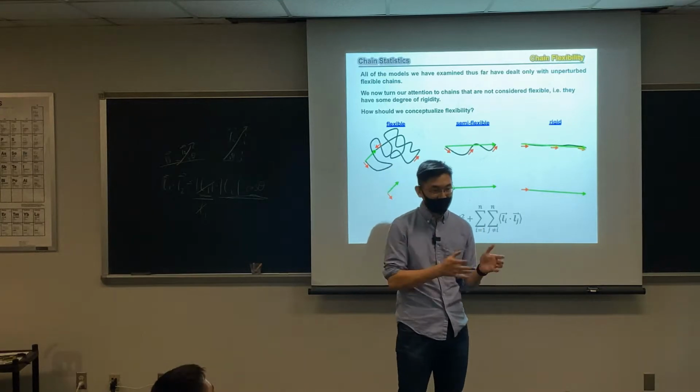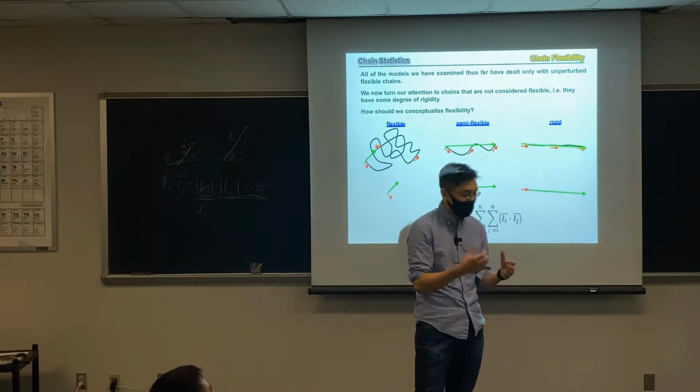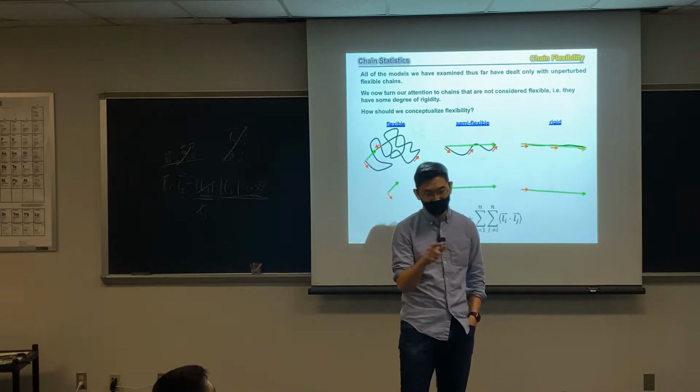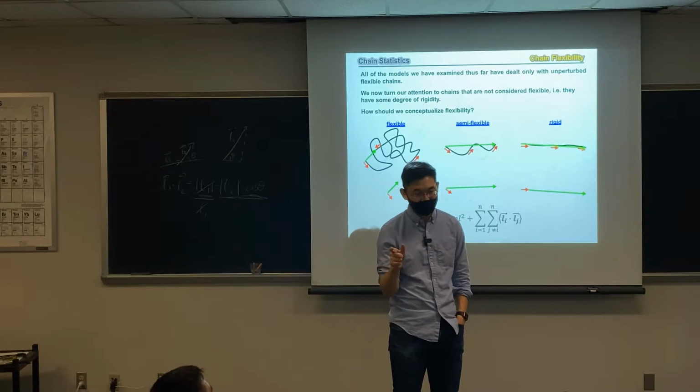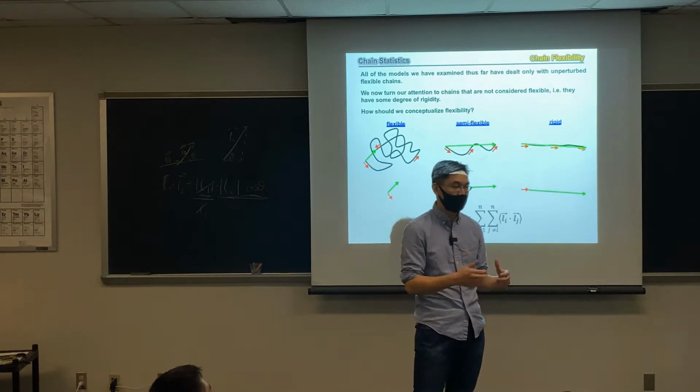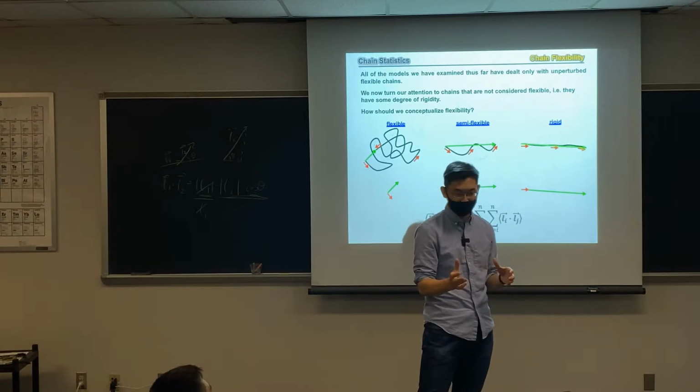So B's physical meaning is just an averaged bond length that gives you the ability to describe the molecule by a freely jointed chain. That's the statistical meaning of B. It's not a direct measurement of how long that length is, because that length is not equal to the freely jointed chain length. It's just a hypothetical length, B, that could translate a real molecule into a Gaussian coil.